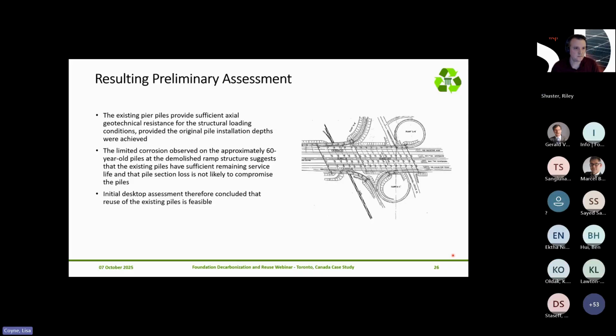So from the desktop assessment process that we had gone through, complemented with this cool opportunity to look at an admittedly small sample set of extracted piles from this structure that was in near proximity to the bridges in question, we have made a preliminary conclusion that both the existing pier piles will provide sufficient geotechnical resistance for structural loading conditions. There's a risk there around the pile length and capacity, but I'll come to that risk assessment in a moment. And from what Riley has explained, a conclusion as well that the limited corrosion that was observed on these extracted piles supports a corrosion rate that would allow a remaining service life of 75 years for the design of the superstructure replacement with foundation reuse on these piers. So this initial desktop process and assessment concluded that reuse of the existing piles is feasible.